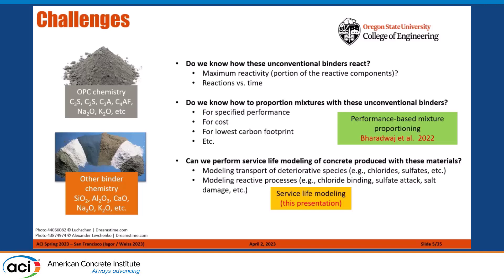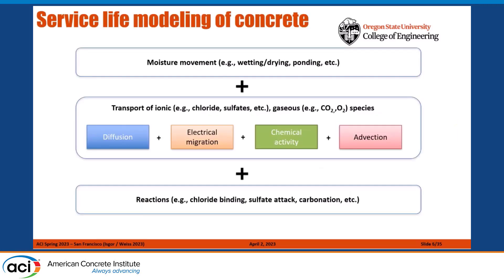We have to understand how these systems will perform and how they will react when external agents come into contact with these structures. This presentation is on service life modeling — specifically, looking at the interaction of external agents with reinforced concrete structures. That can be deicing chemicals, marine salts, sulfates — many different exposure environments can cause problems. They all have a common denominator: some kind of deteriorating species, like ionic species or multiple ionic species, that have to go into concrete, go through some reactions, and deteriorate the concrete. We are very interested in that process.